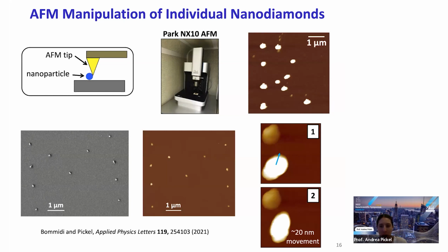And so now if we combine this type of AFM nanomanipulation with the temperature-dependent excited state lifetimes of these NV centers in individual nanodiamonds, then we have a really nice way to do far-field optical single-point thermometry with both high spatial and temporal resolution. And so now that we've essentially proven this capability, we're looking forward to applying it to some of these interesting, motivating applications that I mentioned.